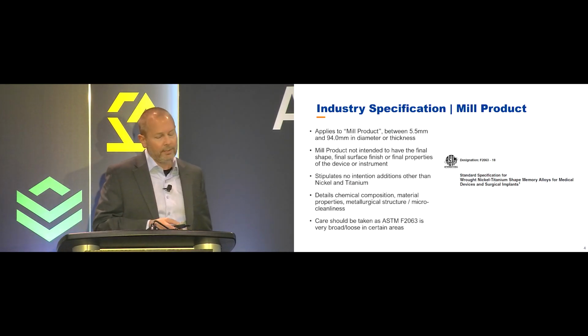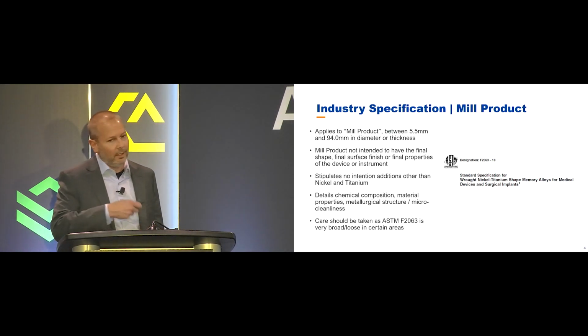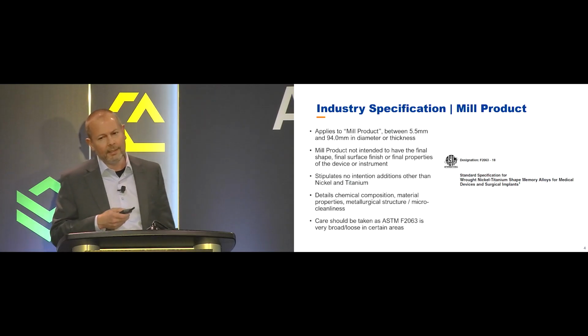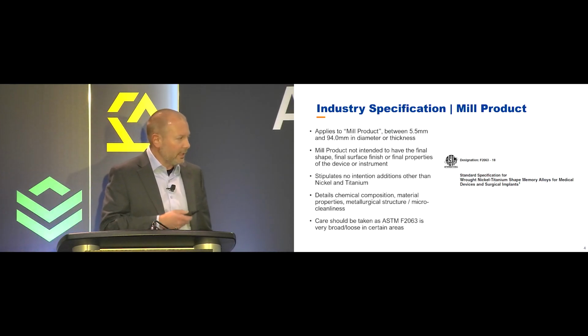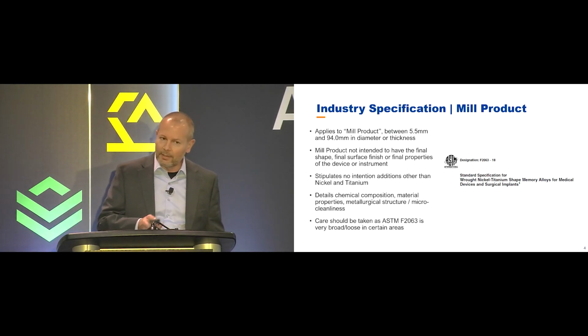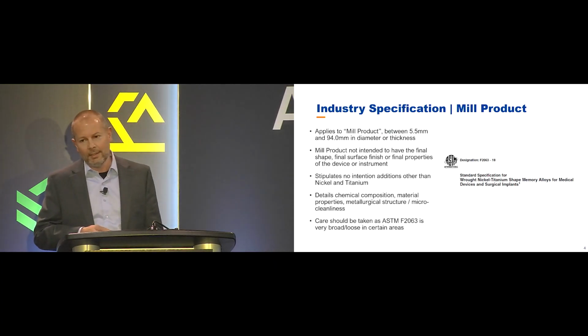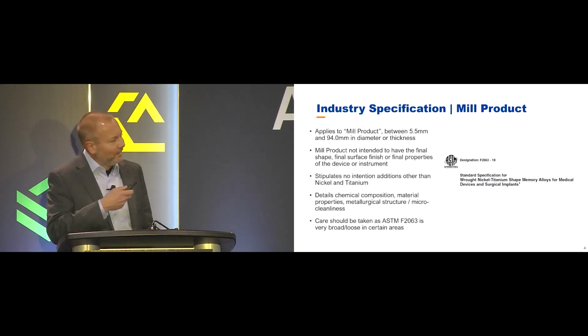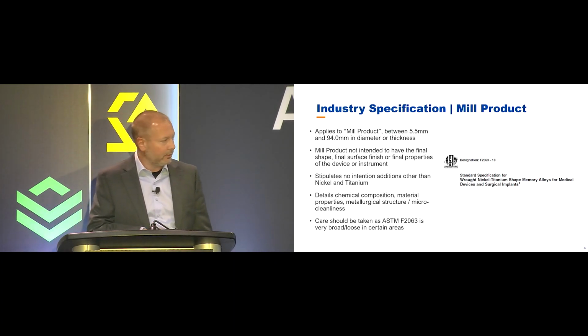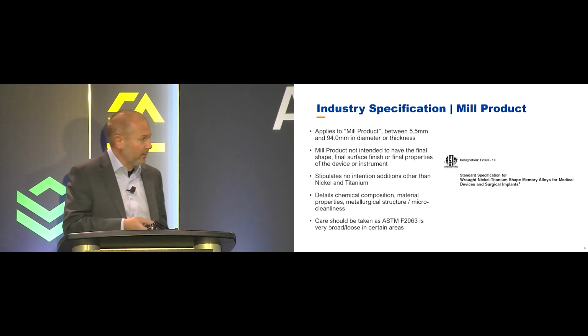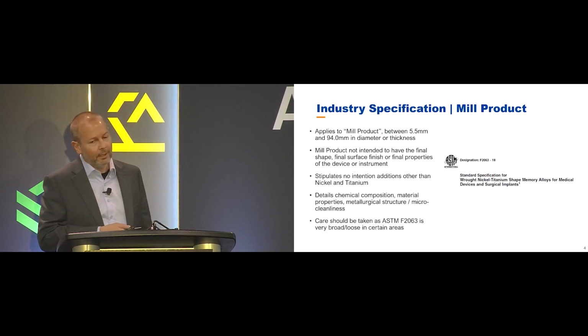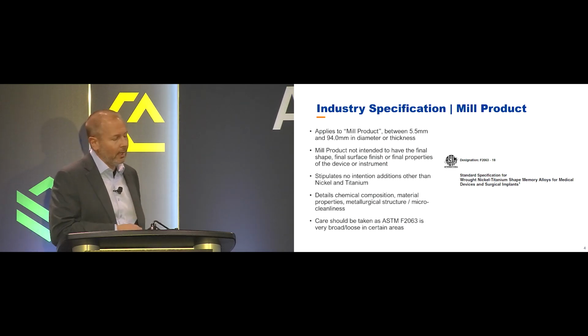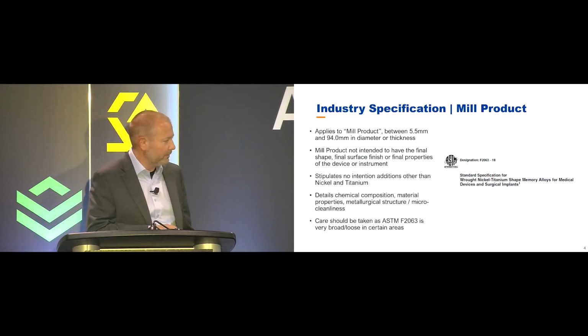It stipulates no intentional additions other than nickel and titanium, so we can't put something else in there. That's why our nickel, titanium, chrome, or cobalt, that's why they don't apply to F2063. That's also why a lot of customers are hesitant to put that in the body because of the FDA. They're concerned they'll have to do a lot of extra testing, biocompatibility. There's a lot of work to be done there. There's customers that use it successfully, but most everybody gravitates just towards the binary for that reason.